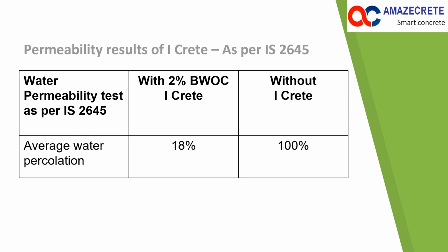So as per IS 2645, when the product is tested without iCrete, the percolation is 100%. As measured as per IS 2645, it is only 18% against the control when 2% by weight of cementitious content is used. So again, it shows the permeability is reduced in a very significant way.